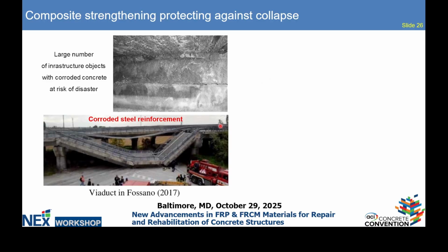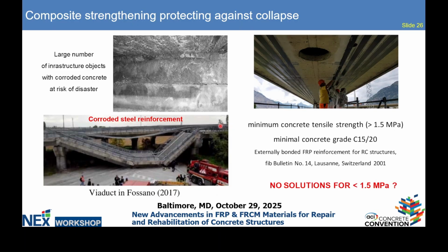It is known that the surface of this concrete is weak due to corrosion. So we have problems with the bonding area when we would like to attach the composite. If we do nothing, we can expect such damages like immediate and sudden falling down of the bridges. So there is, of course, a solution. We can use the composite as the strengthening material, but the requirements of the FIB